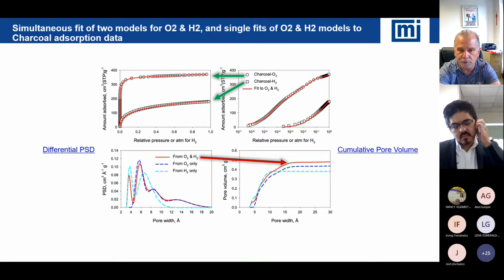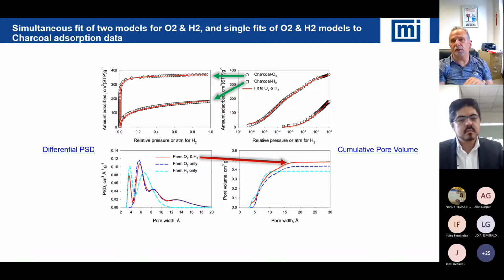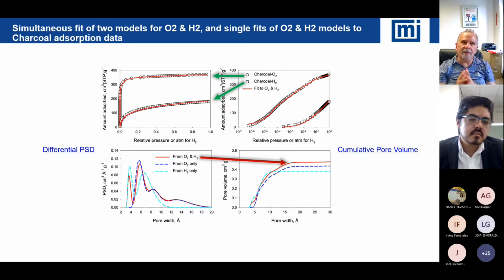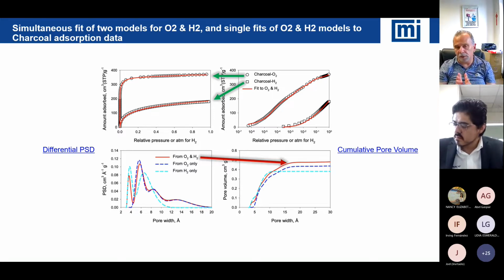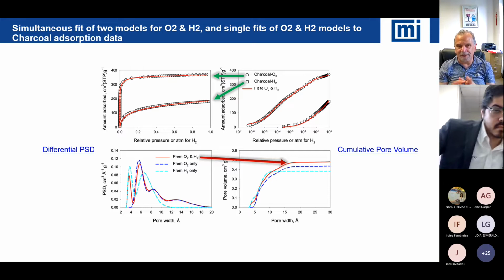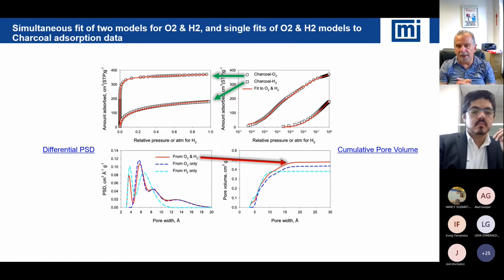On the pore size distribution, the general trend has been to use the same type of characterization you would use for zeolites. So people have practiced quite a bit using, if you want to use classical methods, Saito-Foley for calculating the micropore size distribution. If you're using NLDFT or Monte Carlo, you want to use carbon surfaces. The surface energies seem to be similar and give reasonable results.